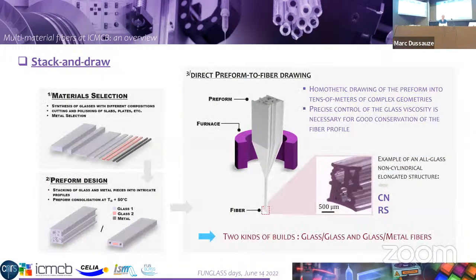Another example of research that we conduct currently using these fibers is what we call the stack and draw revisited. So as you know, there is this method that was historically developed many years ago to prepare photonic crystal fibers. Some fibers are drawn first, and then they are stacked together to make a new preform, which is drawn again. Here we applied the same method, but instead of working with cylindrical fibers, we prepared a lot of ribbons. And then of course we have to assemble the preforms, which means combinations of temperature and pressure. Then we heat under pressure the preforms, and then this preform, when it's stacked together, is drawn again.